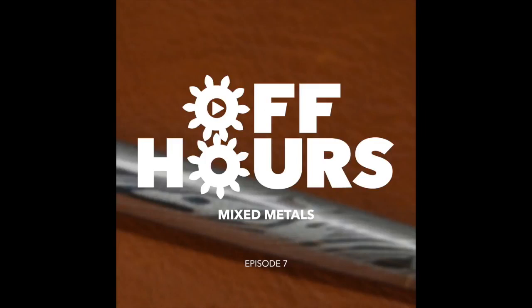Right. Yeah, the other problem that you run into is that you have to work with metals that are fusion compatible, because these are fusing at a molecular level. And so you need metals that are going to fuse together. So for instance, I know Chris has done some work with titanium in, I think it was a Mokume. And so it's a challenge to get the titanium to fuse to other metals, between oxide layers building up and then just them not fusing at a molecular level, because that's what you're doing. You're not soldering them together. Some people have done that where they've soldered the layers of metal together, but that tends not to produce a very good quality billet. You get separation of layers quite easily at that point. Whereas if you get a complete fusion weld between the two, then it's not going to separate. It won't delaminate on you.